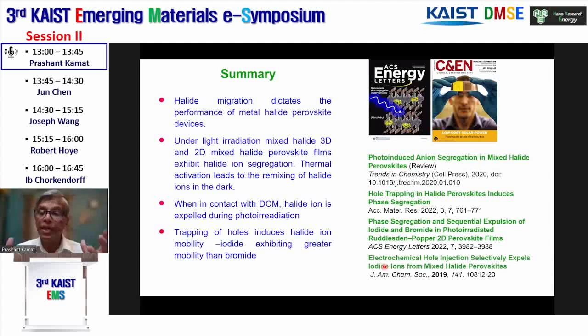And when in contact with DCM, this oxidized iodine comes out of the solution, again showing that the redox chemistry of iodine plays a major role in perovskites. And finally, I showed you that the trapping of holes is responsible for this. There are some papers I've listed here for those who are interested in knowing more. You can follow this through.